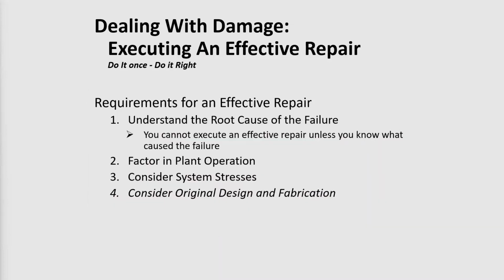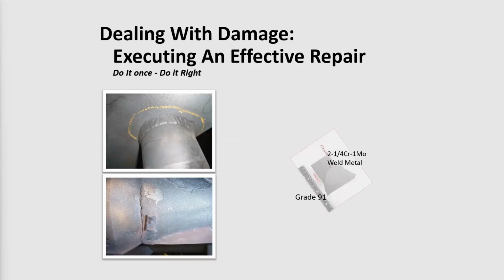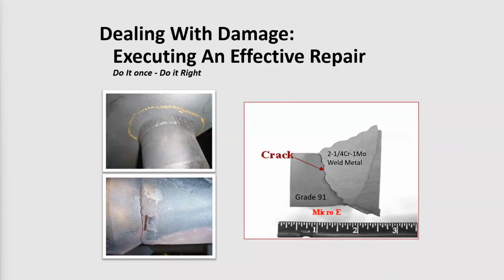And this is just drawing attention to that. Other requirements: consider the original design and the fabrication. I had shown the failure earlier in which, because of the very poor design, there was a premature failure that occurred in a dissimilar metal weld between grade 91 piping and a valve body. If you don't have a good, smooth transition between components, that can lead to enhanced stress concentration and early creep damage, all of which will come into play in determining how the repair should be carried out.